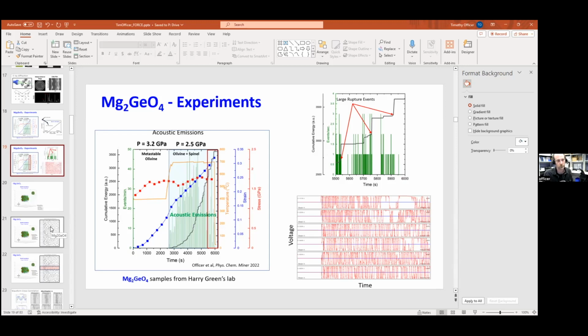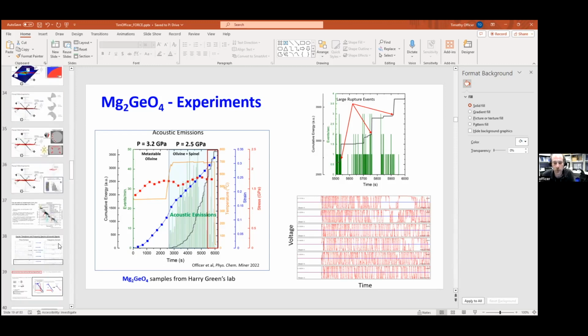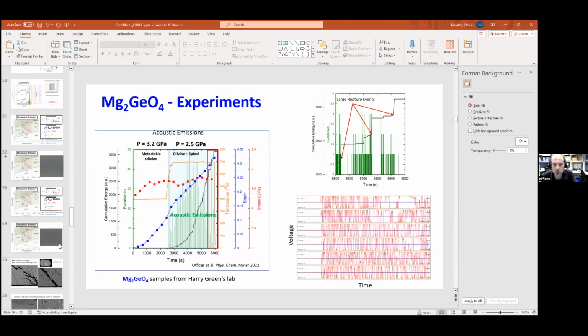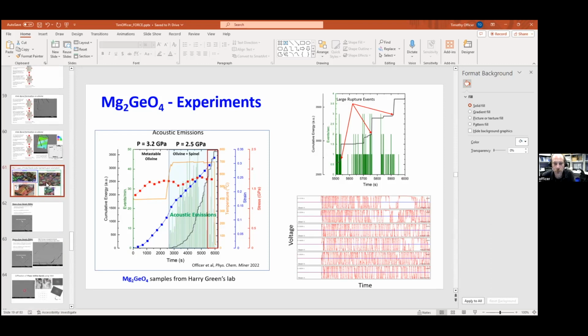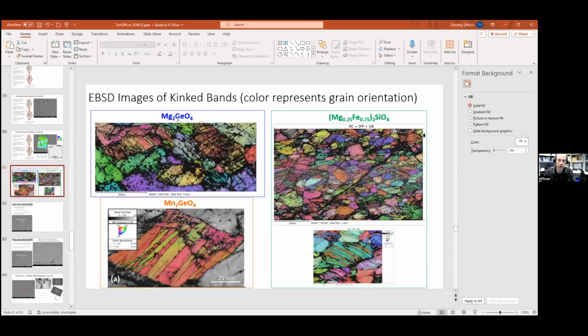She asks, what about offset on the grain boundary where the kink band intersects? No, not necessarily. We actually, here, I'll show you some EBSD images of some kink bands. Here are all three of the materials, the Mg2GeO4, and then the silicate. And you can see that the kink bands are within individual grains.